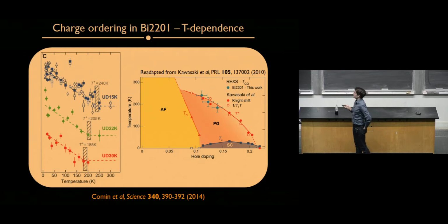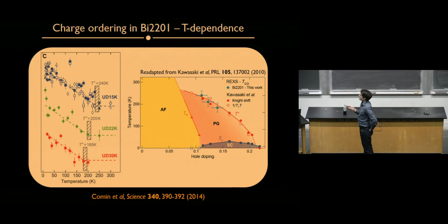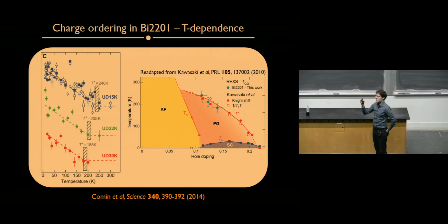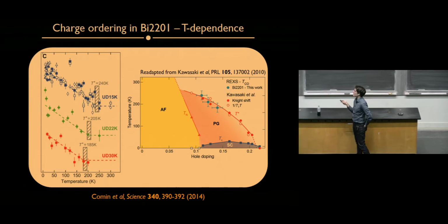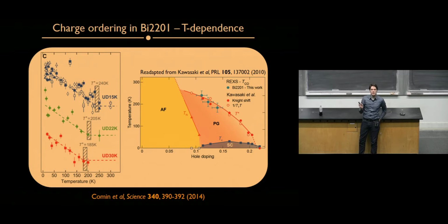So we studied this as a function of temperature, and we realized that the temperatures where charge order starts, where it appears as a function of doping and temperature, so this is the phase diagram, seem to be very close to the onset of a different electronic phase, which is called the pseudogap in the cuprates. Some of you might have heard about it, but it's a very exotic and very mysterious type of electronic phase where people have found all sorts of broken symmetries and now also charge order as a breaking of translational symmetry. This is not a very well understood phenomenon for the physics of cuprates. And what we've noticed is that charge order seems to appear contextually with this pseudogap phase.